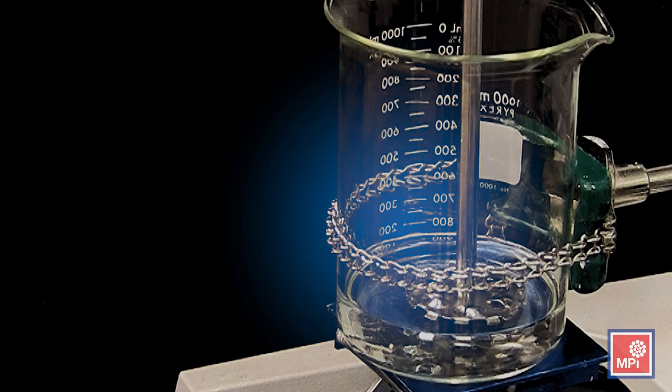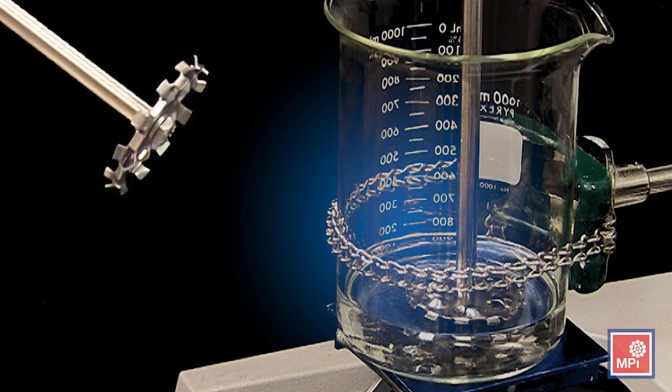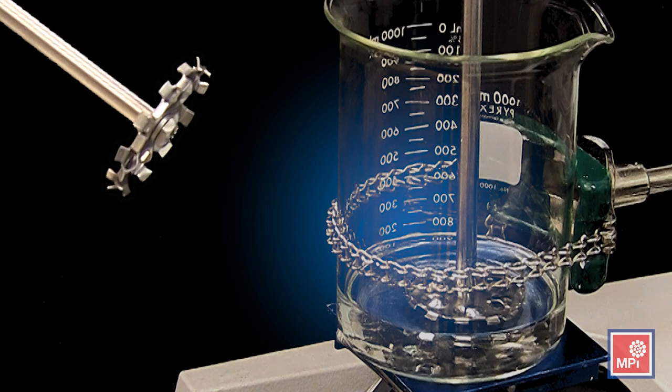We set our container and water under a high shear mixing blade. For best results, we recommend the use of a high-speed impeller disc, which will provide sufficient shear energy to wet and disperse the wax particles and to break down any agglomerates that may be generated during the dispersion process.